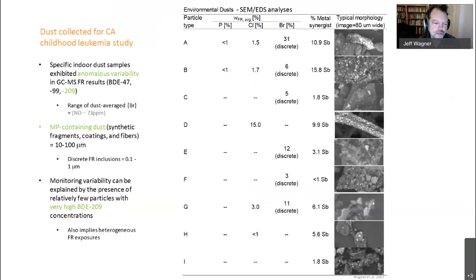These were synthetic fragments, coatings, and fibers on the order of 10 to 100 micrometers. And we saw, once we looked at them in the SEM, that they had discrete flame retardant inclusions on the order of much smaller particles, 0.1 to 1 microns. And we also saw in environmental dust particles, like you see on this slide, that in some cases they had broken up into much finer particles, theoretically as small as the smallest inclusions, which are submicron. So that is somewhat a cause for alarm.